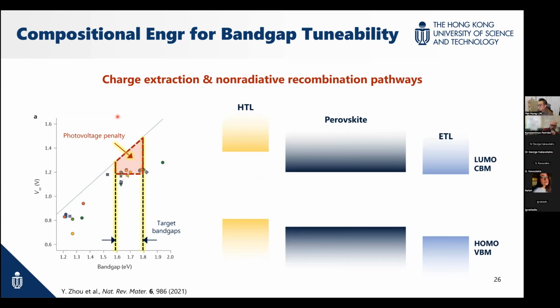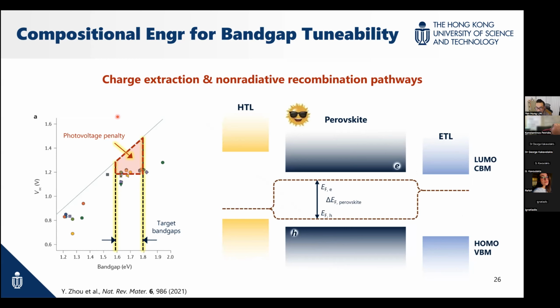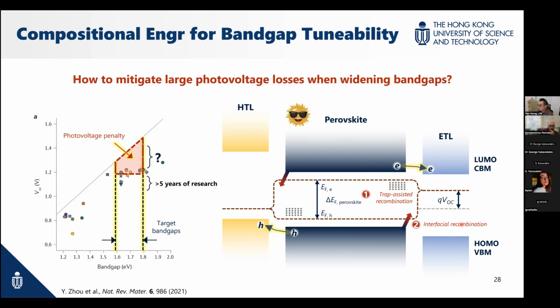This kind of photovoltage penalty actually happens through many mechanisms, especially these two. If today we take a perovskite as an absorber, we shine a light on it, we generate electron and hole pairs, right? Then we have quasi-Fermi level splitting like this. Then we have the electron transporting layer and also the hole transporting layer, trying to take the electrons and holes out of the perovskite. But here, these charge carriers experience trap-assisted recombination, also interfacial recombination. So the voltage is not as high as the intrinsic quasi-Fermi level splitting within the light absorber material.